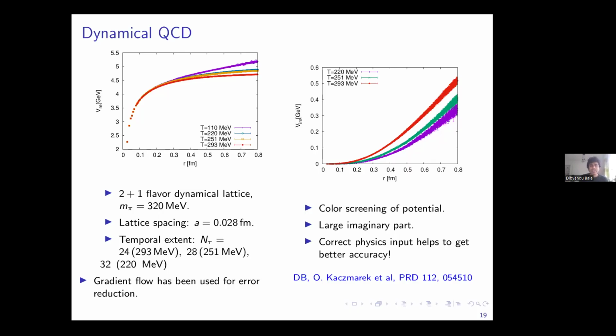Okay, if it had been physical, then I could see some signal of saturation already maybe at these distances. But since the pion mass is very high here, it could happen at a little bit larger distance. When the pion mass goes to infinity, it will never happen. When the pion mass is a little smaller, then it should saturate somewhere. But we didn't go to that region because we wanted to study the finite temperature effect. That screening is not due to temperature, but it's string breaking at zero temperature.